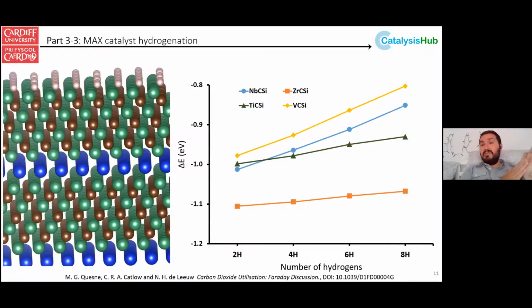So then we thought this was very good. It bodes quite well for the activity of these surfaces. And then we looked at hydrogen loading. So unfortunately, hydrogen loading on these surfaces is very, very exothermic. So we see that the actual change in exothermicity per hydrogen molecule does lose some of that exothermicity, but even where all the holes are filled with 8 hydrogens, the lowest, which is here at vanadium silicon carbide, is 0.8 eV.